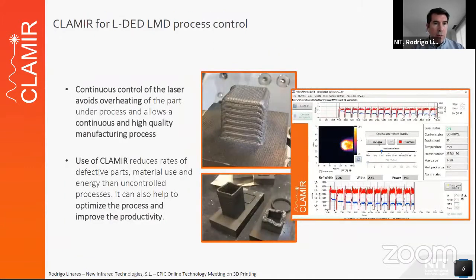I would like to show you the benefit of using Clamir in the control of the laser in LMD processes. You can see that here, an uncontrolled laser power can lead to a defective part, like in the sample of this tube, where there is a clear effect of the overheating that prevented the part from growing, compared to the one on the left, where the process has been done with power control, and you can see that the part could grow perfectly without interruption.